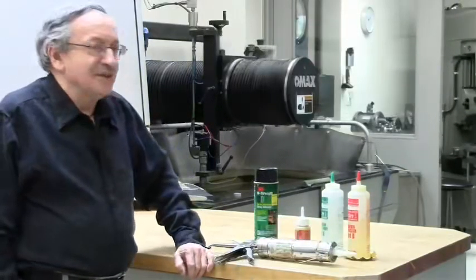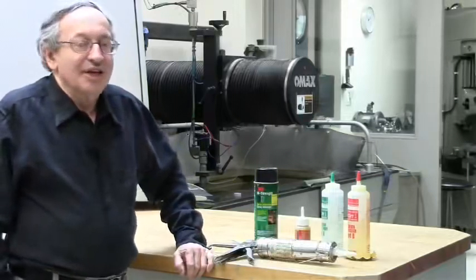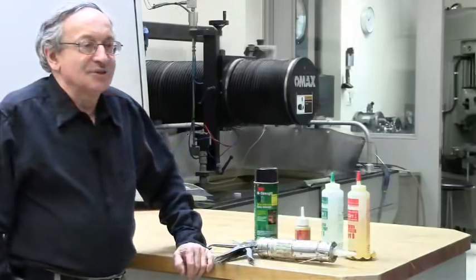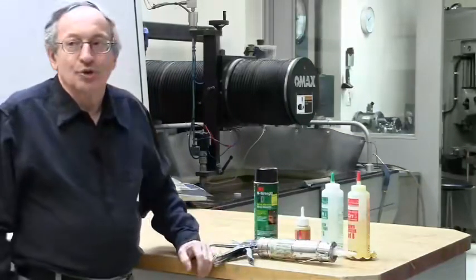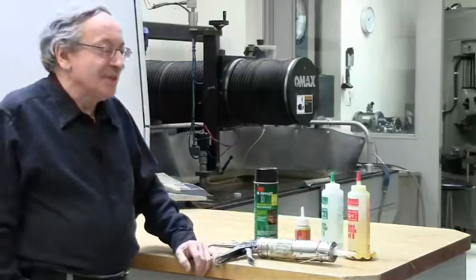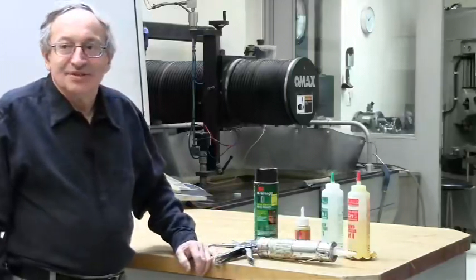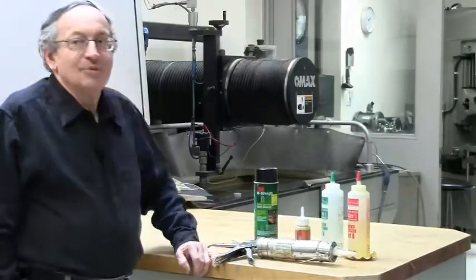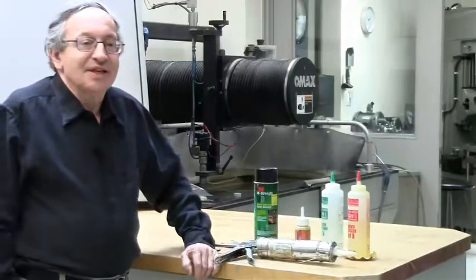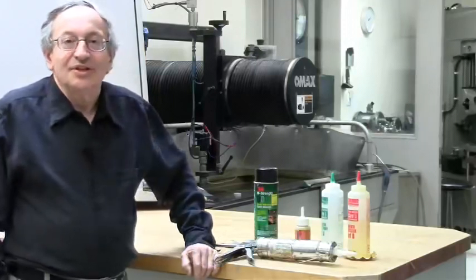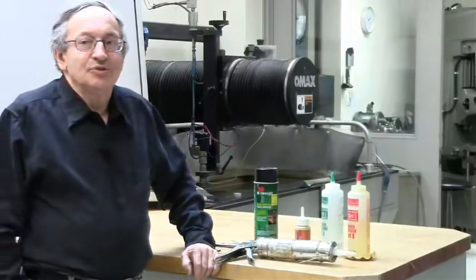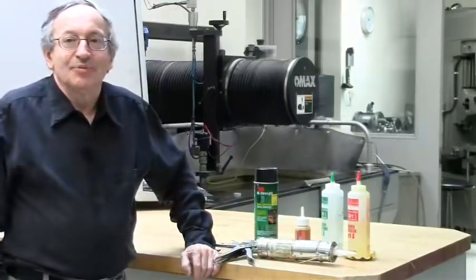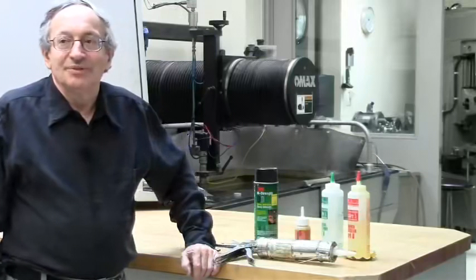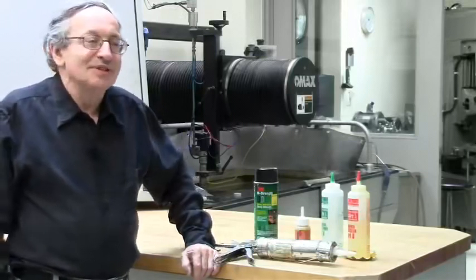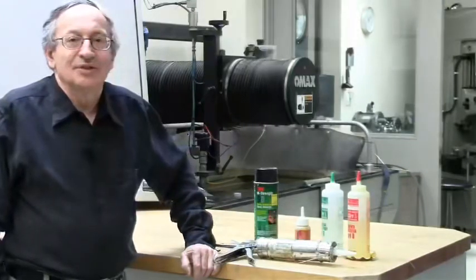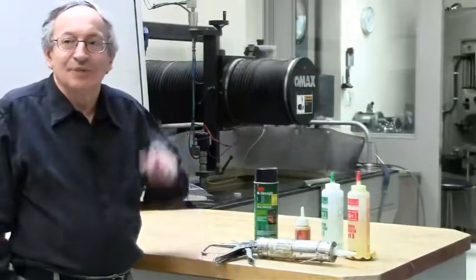Now, they are not very good adhesives for two reasons. A, they are very rigid, so the joint can break very quickly under a shock load. They are very good for rubber because they bond instantly, so they're good for O-rings. But they have another problem which is very devious: they emit some gas slowly. So if you glue anything with super glue and there is any optics in the same box, the optics will fog up within a few weeks and be ruined. And also they have some bad effect on some plastics. They cause the plastics to craze, meaning develop micro cracks.